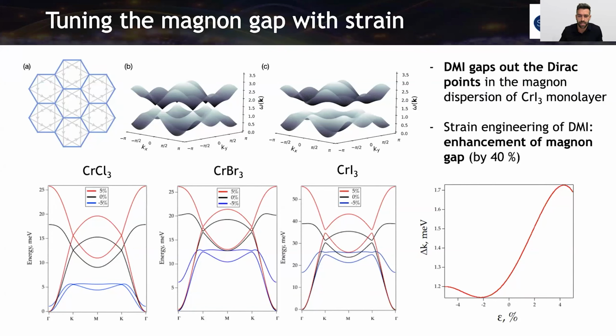Interesting would be to also test, for example, if with a substrate we can get this kind of effects, because the material naturally, when people are measuring the bulk, we have expansion of one axis and a compression on the other axis, but then when we go to the few layers limit, how is this effect going to be in the lattice parameters? But this is what I think of as external strain.